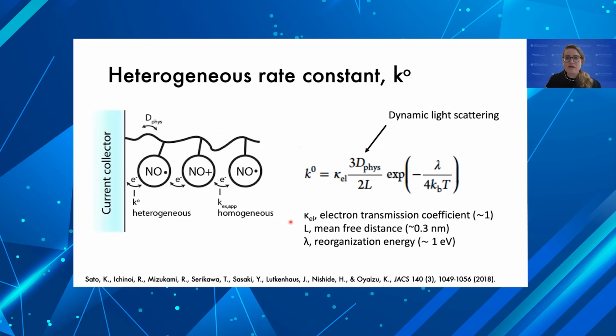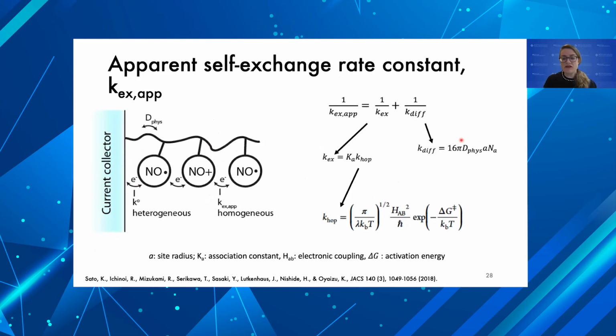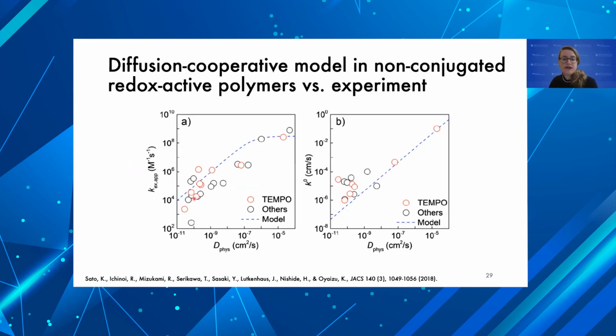If you're interested in the math behind this, we can see how the diffusion coefficient of the polymer relates to the heterogeneous rate constant, where we can measure the diffusion coefficient through dynamic light scattering. We're also working on measuring it through other means currently in my lab. And then you can also see here how the diffusion coefficient of the polymer manifests in the apparent self-exchange rate constant for the polymer. So it's like a modified Marcus-Hush type hopping. And then when you consider the diffusion coefficient of the polymer in this model, which is the blue line, you can see it captures the experimental data quite well.